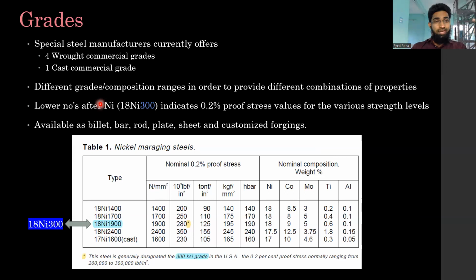So the different grades or composition regions are there in order to provide different combination properties. So why the grades? Because you need an optimal combination of properties suited to specific application. That's why the different grades. And you can see here that we have the four different wrought grades and the cast grade. Different conventions, for example, 18 nickel 1400, 18 nickel 1700, 18 nickel 1900, 18 nickel 2400, and then the cast grade. But the most common is 18 nickel 1900 in the tool and die industry.